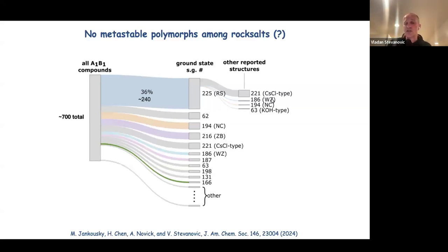Wurtzite is known, as I showed you a moment ago, to transform from rock salt quickly into wurtzite or the other way around. Nickeline is the same. So essentially, all these 240 that crystallize in their ground states as rock salt don't really have any metastable phases. If they have higher energy structures that have been observed, they are all short-lived. So that's the point.